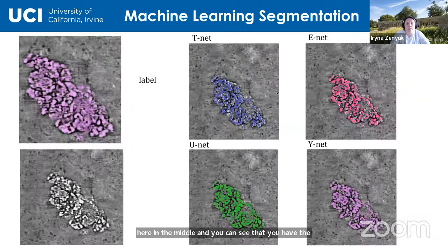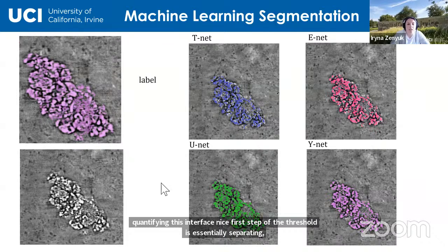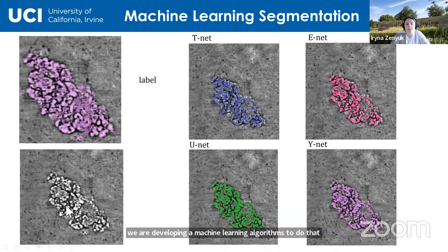So typically, the next step is how do we quantify the data? And quantifying data is another challenge in the field, because if you think about these interfaces, they are not so clean, right? So this is lithium symmetric type of battery that has been cycled. And this is polymer electrolyte here in the middle, and you can see that you have the dendrites on the interface. You have some layer that has combination of pits and dendrites, and quantifying this interface needs first step of thresholding, essentially separating what is dendrite and what is not. So in this sense, we are developing machine learning algorithms to do that, because if you look at this typical dendrite, for example, it has a lot of grayscale variation across.